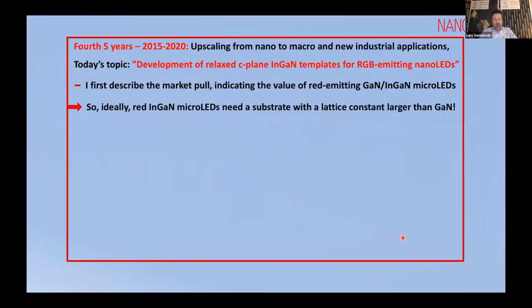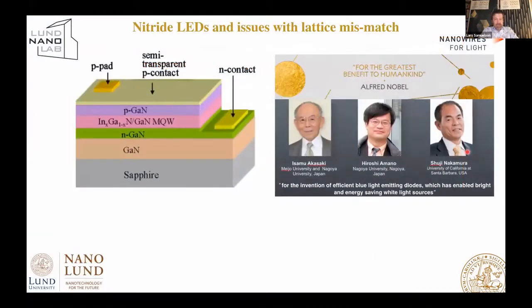So that brings me back to summarize what all this market pull tells us, at least tells me. Ideally, you need red indium gallium nitride micro LEDs that can generate the red, but it seems that you need a substrate with a lattice constant that is larger than that offered by gallium nitride as the traditional host material. So let me put that a little bit into perspective.